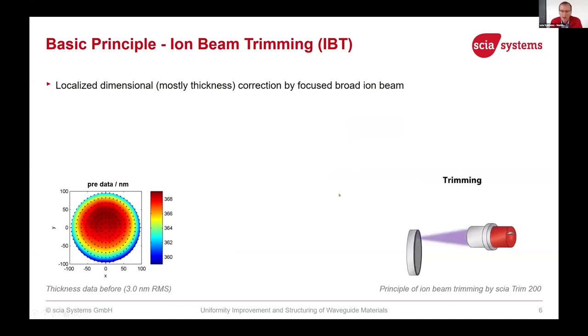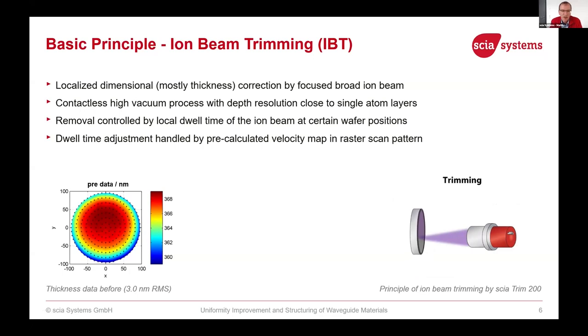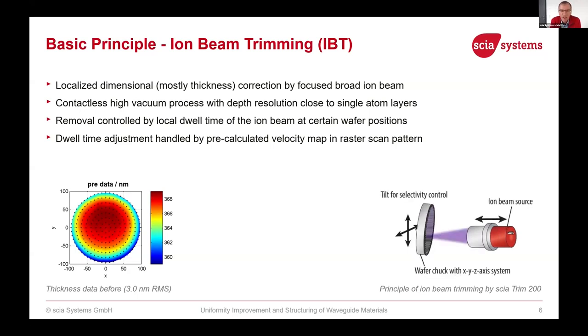In ion beam trimming, you see it in the schematics, you move a wafer in front of a broad beam ion source with a focused beam, and you remove material at certain positions. It's a contactless high vacuum process with a very good depth resolution, close to single atomic layers. The removal is controlled by the local dwell time of the ion beam at a certain wafer position, and the dwell time adjustment is pre-calculated and then transferred into a velocity map for this raster scanning. We can also tilt our substrate to a certain angle to achieve certain improvements.